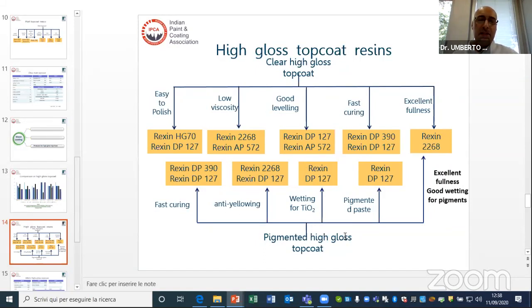Speaking about pigmented system, we can see again that there's a product with fast curing properties, good anti-yellowing properties, so it can be used also outside. It has very good wetting properties for titanium dioxide, but it may be used also to make pigmented paste, so it has very good properties also towards all the other pigments that we can find on the market. It is specific for titanium dioxide, but its behavior with all the other pigments is very good.